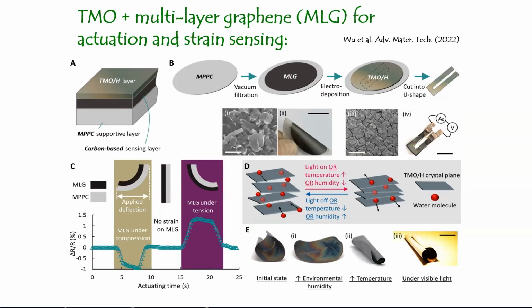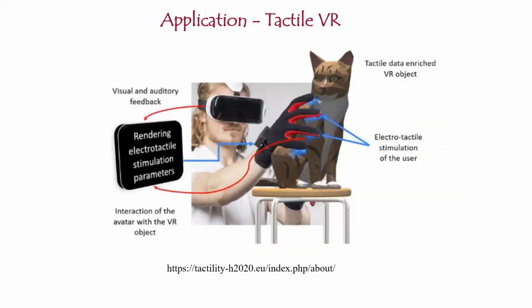This is another interesting material system where you use the TMO together with this multi-layer graphene. Multi-layer graphene is good for, again, strain sensing. So the problem with hydrogel is that they will dry up over time, but not for graphene, okay? And then graphene, because of the overlapping graphene flakes, so if you strain the system, the electrical resistance will change because of the conductive path length will change. So that is also a good strain sensing system.